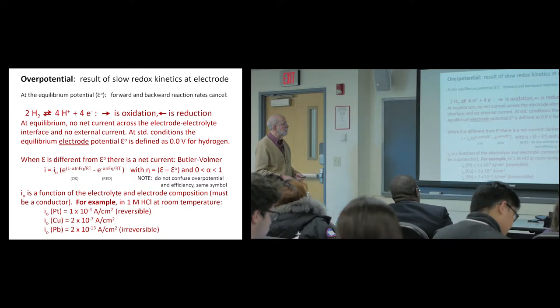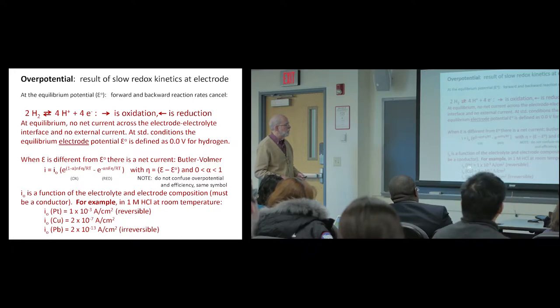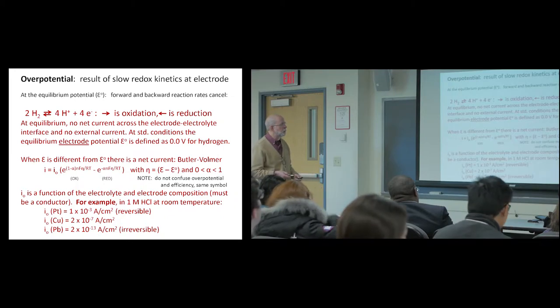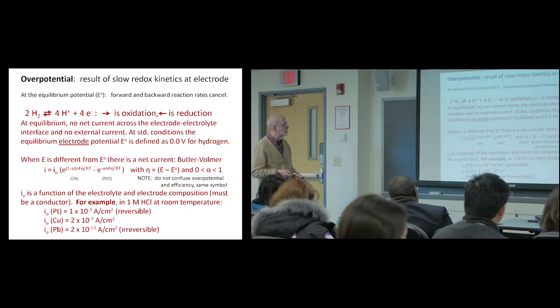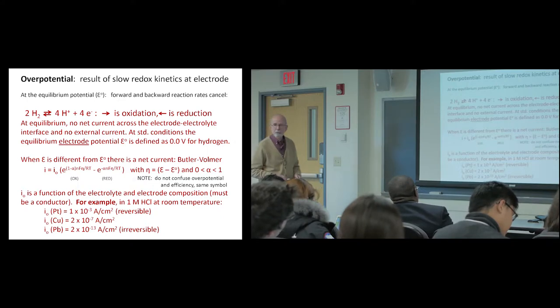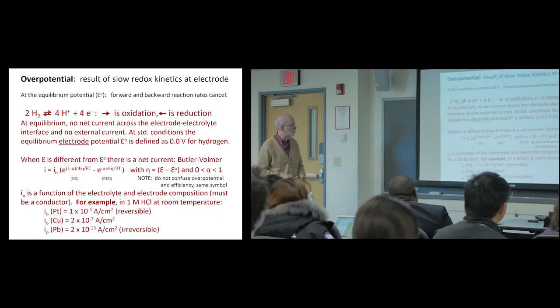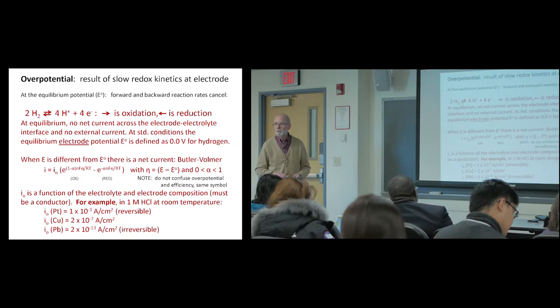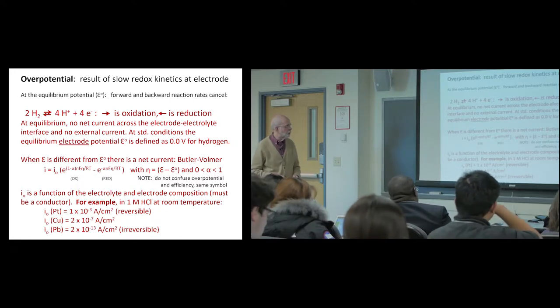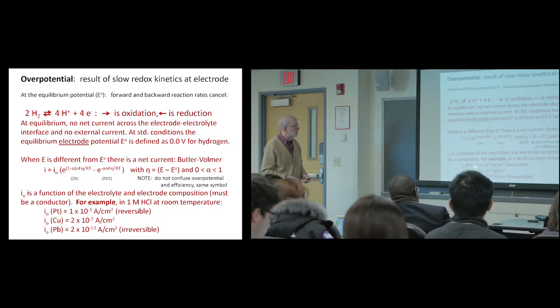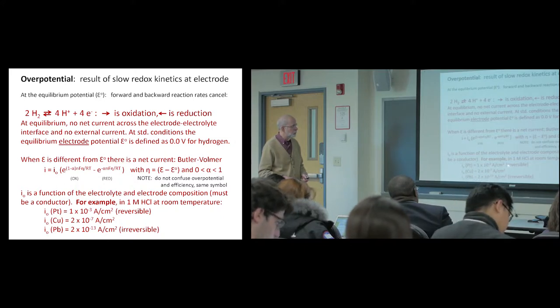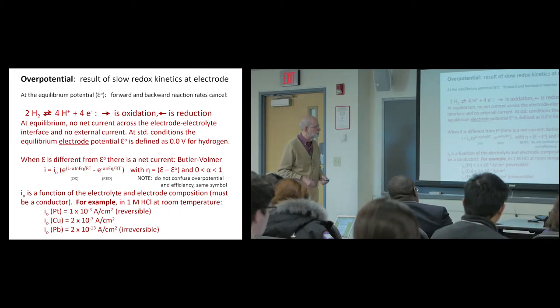So let's just look at a cell that's made in one molar HCl at room temperature with different electrodes. With platinum, you get an exchange current of about 1 milliampere per square centimeter. With copper, it's much smaller, and lead, it's teeny tiny, 10 orders of magnitude lower than for platinum. So platinum is a super catalyst. It's really a great one. Anything that has a large I zero is also sometimes called reversible. And if it's a low number, it's usually called irreversible.